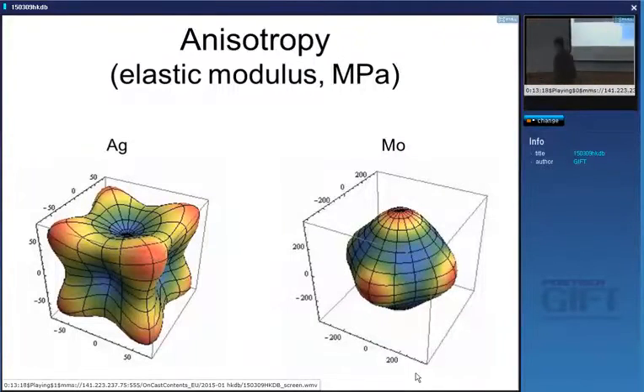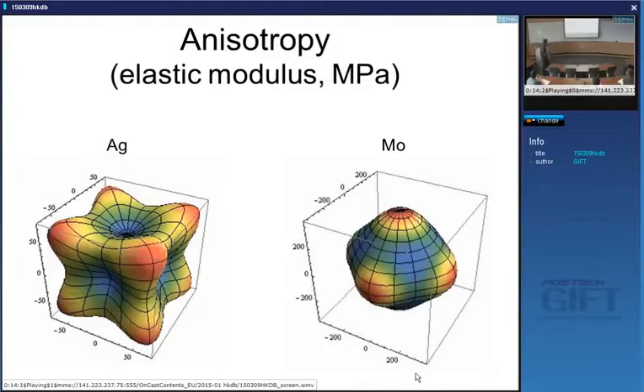So this illustrates how the properties vary as a function of direction in a single crystal. So this surface, a vector from the center to this surface, represents the modulus. In a single crystal of silver, you can see that the modulus is not constant. It varies as a function of directions. There will be certain soft directions which, if you stress along soft directions, then the amplitude of vibrations will be large. If you stretch along a stiff direction, then the amplitude will be small. Okay? And this is in the case of a body-centered cubic metal, molybdenum, where again you see that the modulus is not identical.